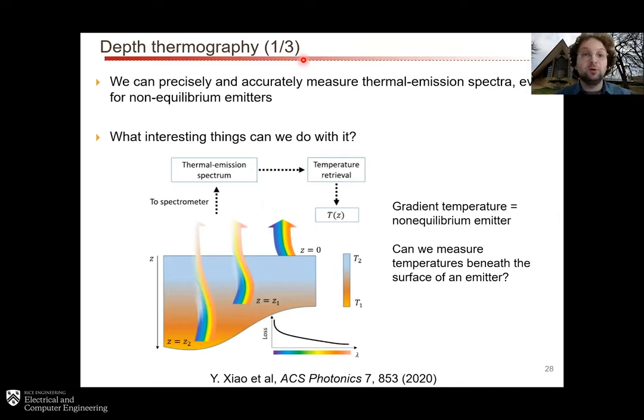It's a technique that we called depth thermography. So thermography is the use of infrared imaging to measure temperature, to do remote measurements of temperature. And depth thermography is a very similar technique that enables the measurement of temperature not just at the surface of objects, but also as a function of depth. So in certain circumstances, and granted those circumstances are rather limited, we can take an object and do a thermal emission measurement. We can measure the spectrum of thermal emission that comes out, and we can do a temperature retrieval where we essentially invert that spectrum, compare it to a model, do some fitting, and find the temperature not just at the top surface of the object, but also as a function of depth.